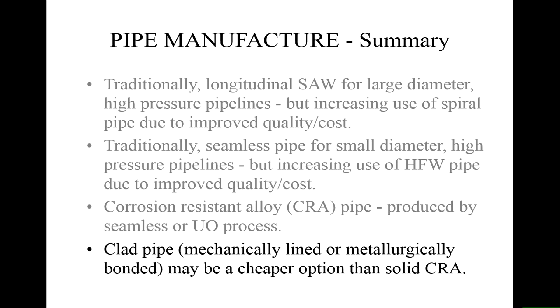Corrosion-resistant alloys, as I mentioned before, may be as much as 16 times the cost of the carbon steel pipe. And that means that if you've got a very long pipe run, the materials costs will become too much. Whereas if you clad a carbon steel pipe, or you use a lined metallurgically bonded system, you can save money and still have that high corrosion resistance. But then you have to deal with the fact that you've got a two material hybrid system. It doesn't behave quite so simply.